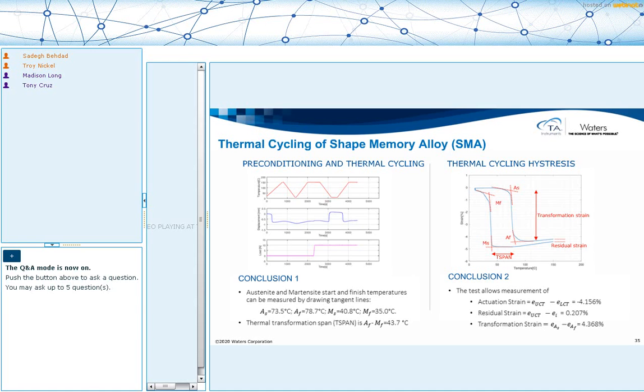And after we are sure that all of the sample is at the same temperature, we increase the load to 10 newtons. So a steep increase in load to 10 newtons. We are maintaining that 10 newtons for the rest of the experiment. And then we start to cool the sample. So in the beginning, if you start looking at the displacement versus time, which is the middle plot, at around, say, 2800 seconds, you see that it starts to slowly decrease. So this is a contraction. Around 3000 seconds, that's where the martensitic phase transformation starts. You see that the length is increased, so the displacement becomes more positive. So we are looking at almost 1 millimeter of displacement in a 20 millimeter long sample, about, say, 4 to 5%.